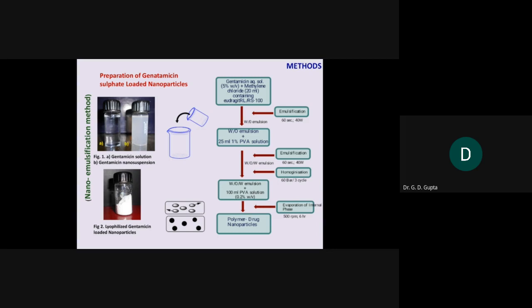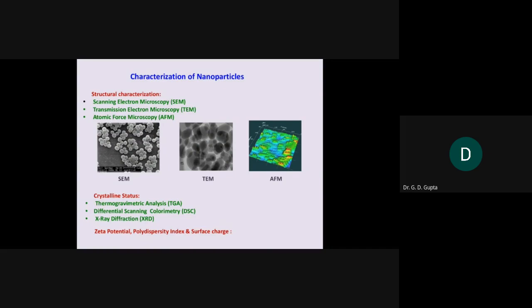So this emulsification method was used. Next, after getting the nanoparticles, we characterized them for surface and structural characterization, that is scanning electron microscopy SEM, transmission electron microscopy TEM, and AFM atomic force microscopy. You can see the figures of the different techniques. The particles are very spherical in shape, as the SEM image depicts, and in the SEM image you can also find the particle size is more uniform. Later you will see the polydispersity index value, which signifies the uniformity in the particle size. Later, for the crystalline status, we performed thermogravimetric analysis, differential scanning calorimetry, and X-ray diffraction. Apart from that, we performed zeta potential, polydispersity index, and surface charge measurements.